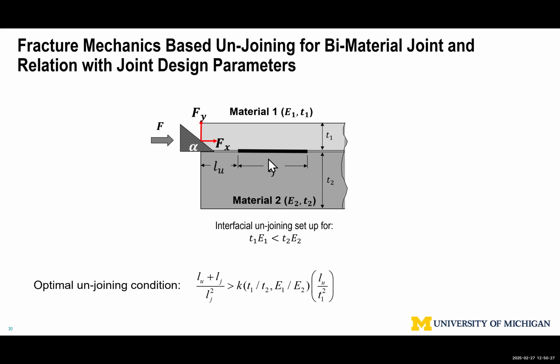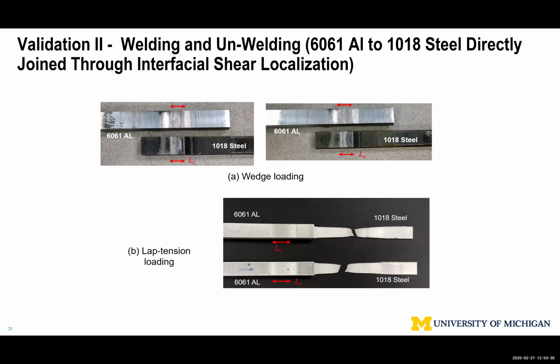And that mechanism should never be triggered during operation, during service, but only triggered by a technician when they want to open things up. So with that, for aluminum and steel, we produce an almost pristine bonding surface on opening. That means almost immediately you can rebond them, rejoin them, reweld them as needed. If you use a tensile load, simulating structural loading in a service environment, you develop fracture on the steel side or on the aluminum side, which is desirable, giving you maximum energy absorption and also the best fatigue fracture resistance.